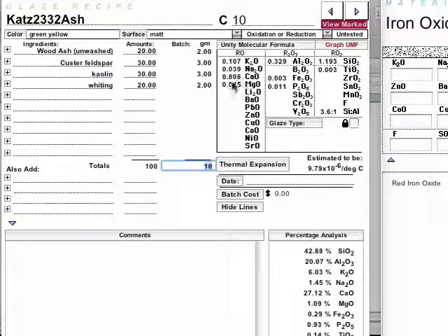Those are pretty small amounts. But 0.8 moles of calcium, and all the glazes that we're looking at today are going to have about that amount of calcium and then various amounts of other things. This over here is the amount of alumina, and alumina controls the running in a glaze. But in these glazes it also controls melting. As the amount of alumina goes down, the glaze is going to melt harder and harder, oddly enough, till the silica gets down low. It's complicated.